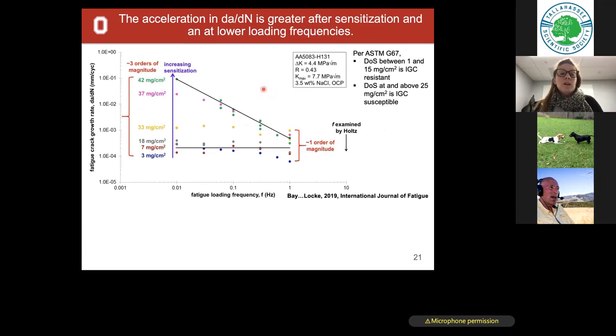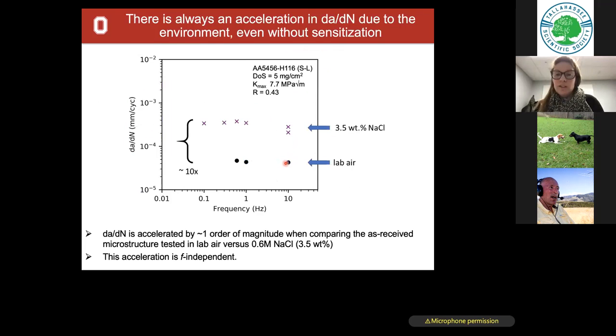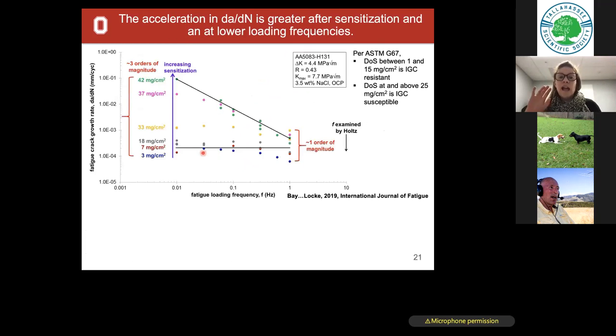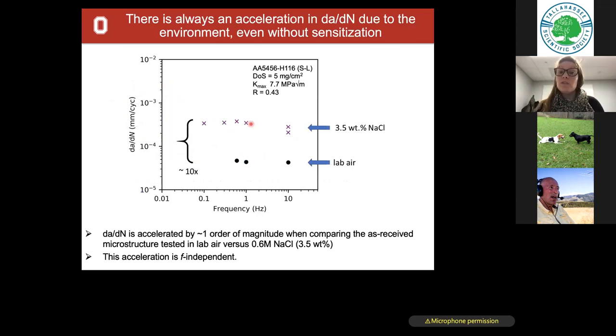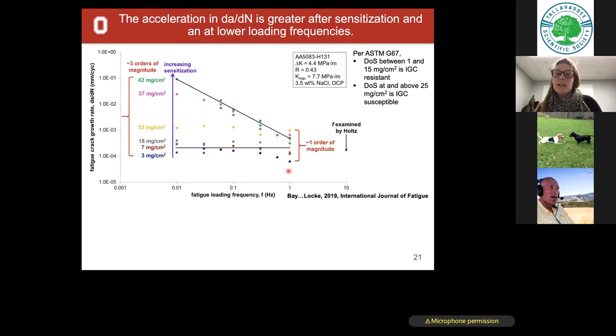Okay, so what we see here, and this is for just one of those aluminum magnesium alloys we looked at, right here is that 10 hertz. Right here is 1 Hertz, right? The data for lab air is no longer on this plot because it's sitting down here. Here is that data with very little, what we call sensitization or essentially baking. Very little is down here. You see a frequency independence, just like you saw up here. So it doesn't matter. I can load it fast, I can load it slow.